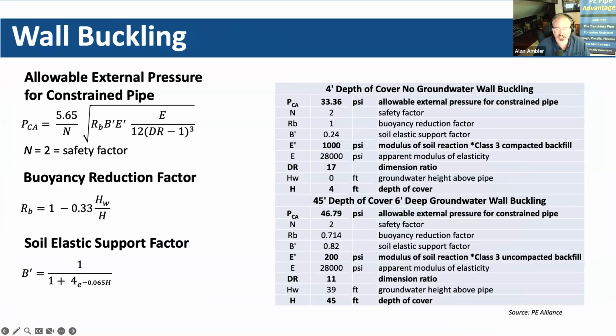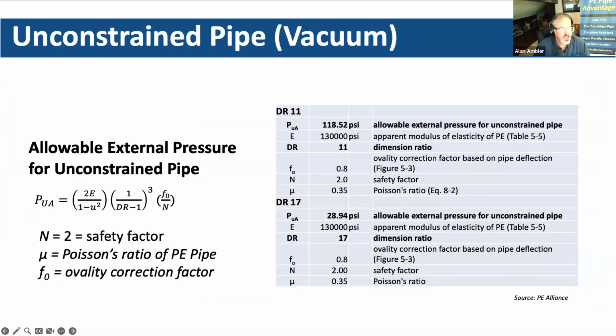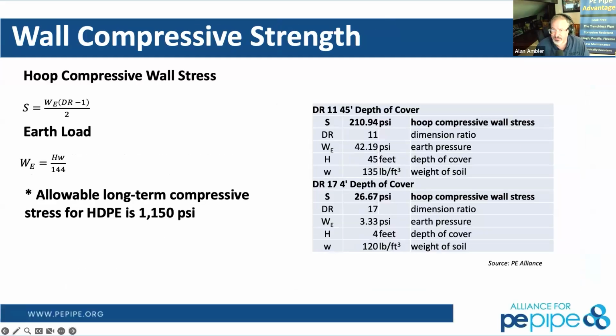So here's wall buckling. This is just another part of the calculator as we go through, and we take that specific scenario that we looked at to be able to calculate those. So for vacuum pressure, what we're looking at is if we have full collapse within the pipe, and we'll see a DR11 can withstand 118 psi versus a DR17 at the 29 psi that we're looking at. So with a thinner wall pipe, we will need to look at vacuum pressure if we expect to have some type of a break within that pipe. Vacuum pressure happens when the pump turns on, or if there's a break in a force main on a major hill or something like that. We'll be looking at that.